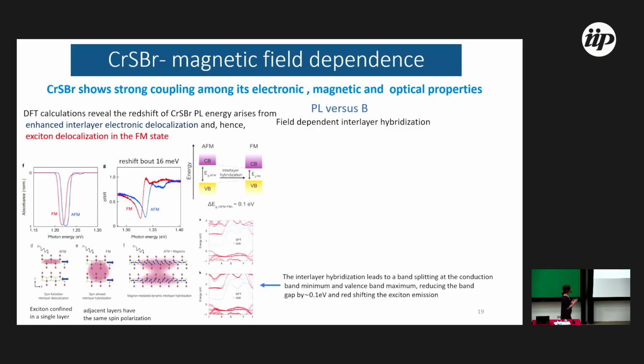So this, I will call CrSBr, or CSB, because it's much easier to pronounce. And it has a strong coupling between its electric, magnetic, and optical properties. It means that you can use the exciton as a sensor of the magnetic phase, because the energy of the exciton depends on whether it is in the ferromagnetic or antiferromagnetic phase.